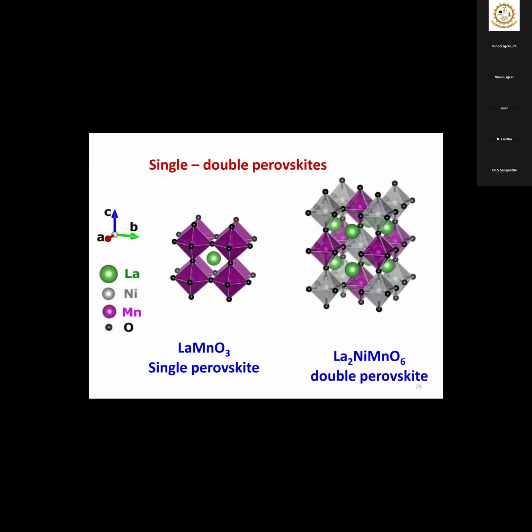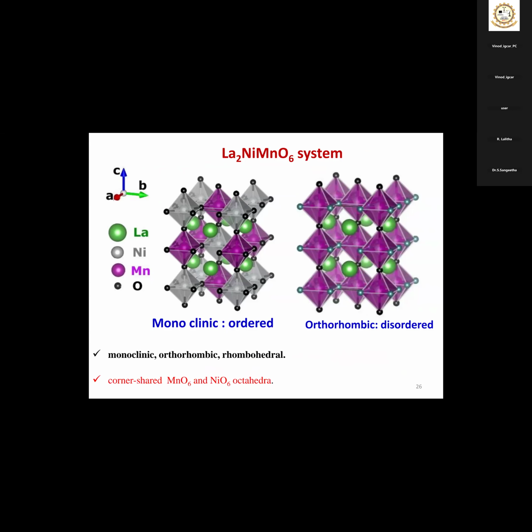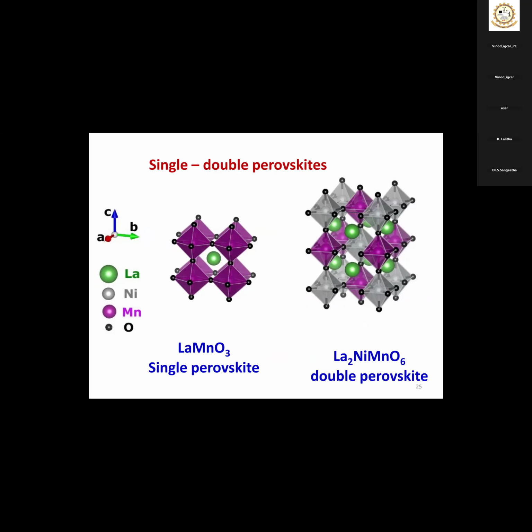Actually, this is a single perovskite crystal structure. So you see LaMnO3. La2NiMnO6 is a double perovskite. That transition I will explain. Okay, that slide I missed. Fine with this. LaMnO3 is a single perovskite. It expands in all 3 directions to give the unit cell. Suppose one of the manganese sites you replace with nickel. Now you see, because of symmetry, your primitive unit cell is now doubled.